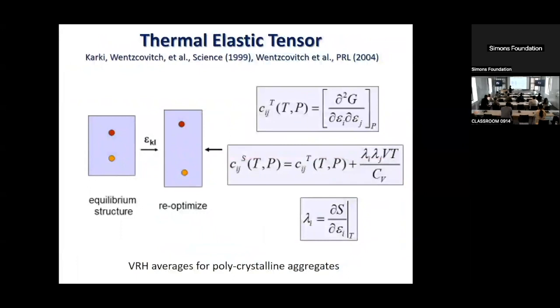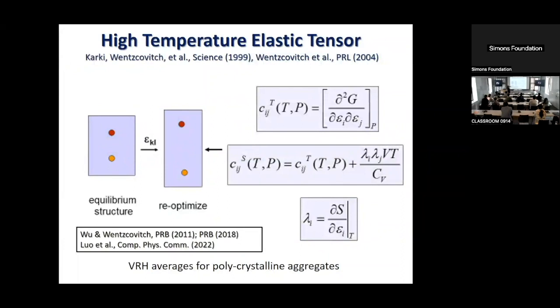We needed the adiabatic elastic coefficients, and there's another correction there. As you can see, this is the high throughput nature of the calculation that we started doing in the late 90s. Today, it has been greatly facilitated by semi-analytical expressions for this quantity. Essentially, we need mode Gruneisen parameters and strain Gruneisen parameters in order to carry out these calculations more efficiently.